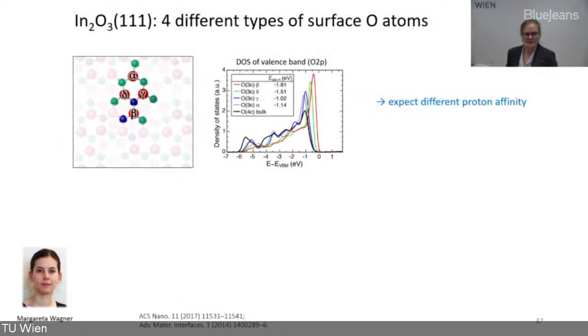We call these 4 different oxygen atoms alpha, beta, gamma, and delta. All of them have a different electronic structure. This plot shows the valence band, the local density of states, with different colors for the different oxygen atoms. The red curve is shifted towards zero - here is the valence band maximum - so this one would be the most reactive, and the others less reactive. So we expect a different proton affinity, meaning different strengths of proton binding, on each of these.